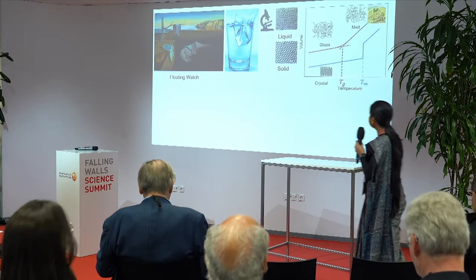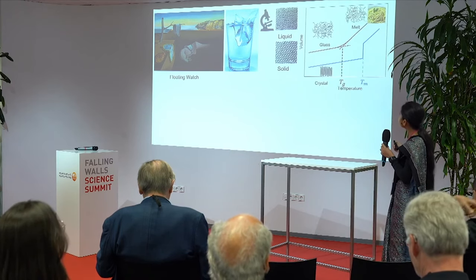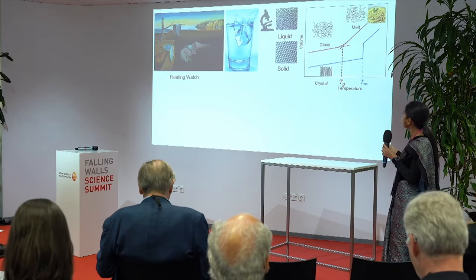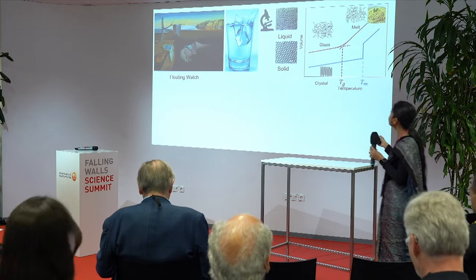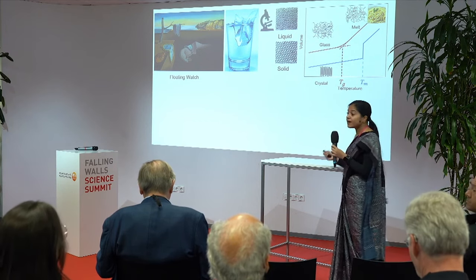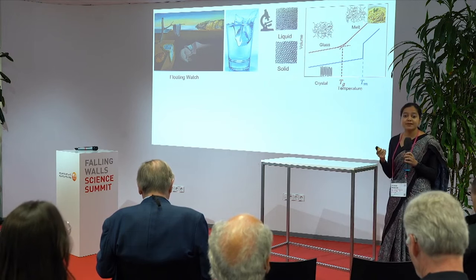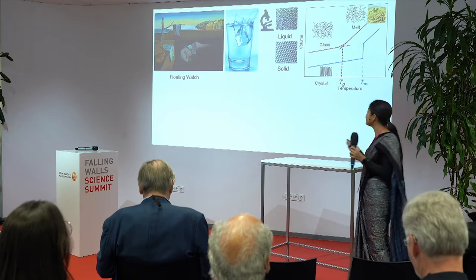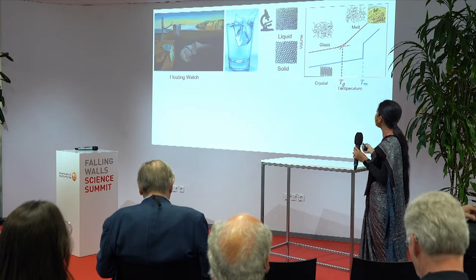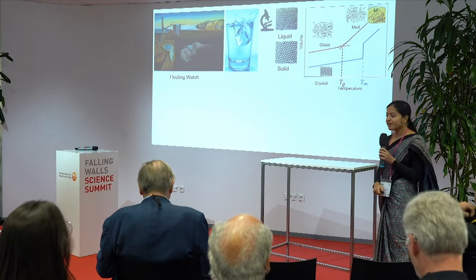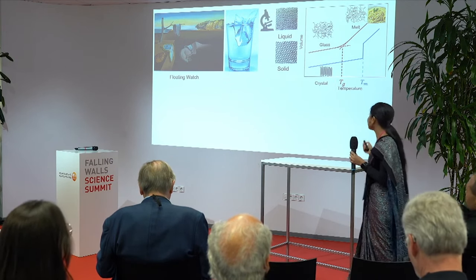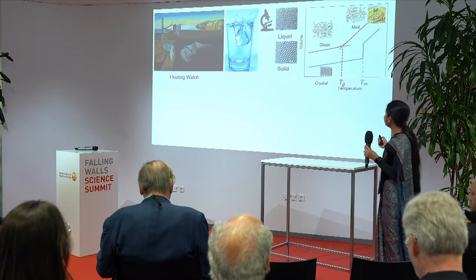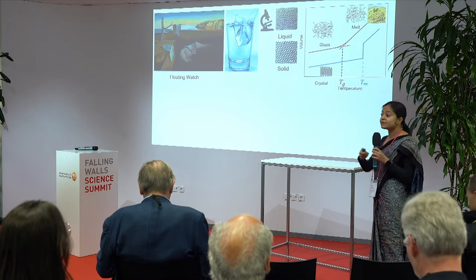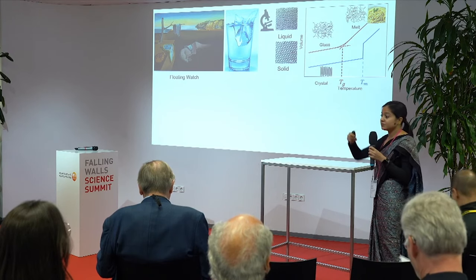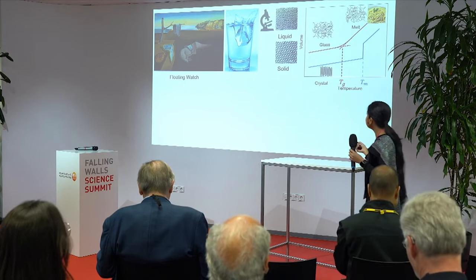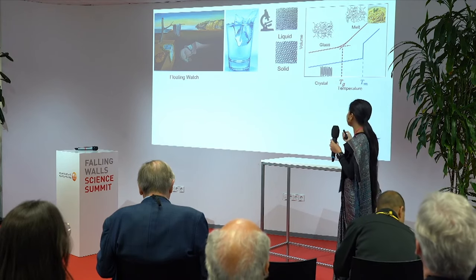So in the phase diagram, going from liquid to crystal, there is a first order phase transition at the melting point. However, if we cool the liquid very fast, the system doesn't get enough time to nucleate, nucleation is suppressed, and it ends up in the glassy state after the glass transition temperature. I am pretty much interested in polymers. For polymers, crystallization is even more difficult because it's a long molecule, so finding order is even harder. So often it ends up in the glassy state.